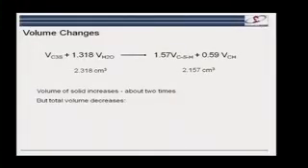Okay, and we haven't just got C3S. If we write down the reactions for the other phases, they're all slightly different. Overall, it comes out about double. But what's more important is that you see the total here is slightly larger than the total here. That's what you have to see in this slide here. That overall, on hydration, you slightly decrease the total volume. And the decrease is what we call chemical shrinkage. And in this example of C3S, it's about 7%.